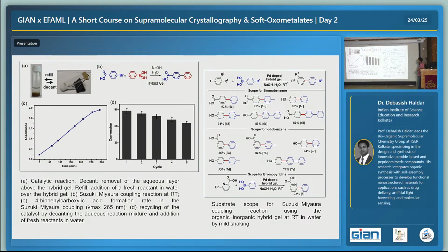And this is the substrate scope. So we can do this with the brominated compound, with the iodobenzene, or with the pyridine unit as well. So we have a lot of substrate scope for this kind of reaction. So the same catalyst we can use multiple times. We can do the Suzuki coupling reaction at room temperature, and in mild condition without stirring, it's just shaking, and we can easily isolate the product simply by acidification and then filtration.